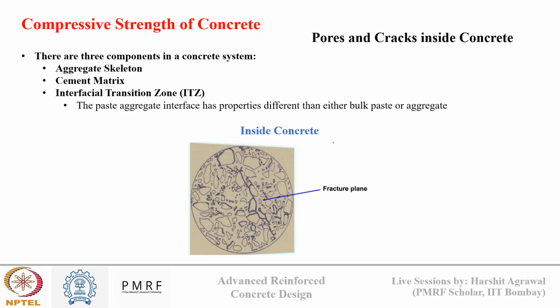Now, in compression, when we talk about cracking of concrete and failure, it is governed by the pores and the presence of initial cracks inside the concrete, because they give the weak link for crack growth. So there are three components in the concrete system: the aggregate skeleton, the cement paste, and the interfacial transition zone. This interfacial transition zone is the interface between aggregate and cement paste, and these zones have more porosity and cracks than the other two parts. So that's why when we talk about failure, the cracking in concrete passes through this interfacial transition zone, which we can see in this image also, the fracture plane, and how it is propagating inside concrete.